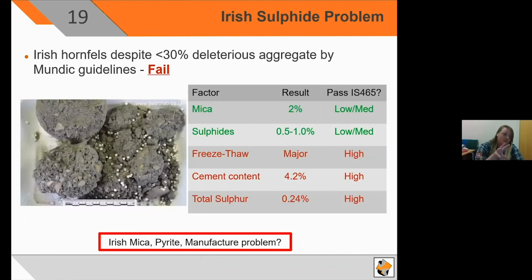So here's some figures from this particular type, which we did as a research and development task. Mica, 2%. That would theoretically be a low medium classification, if not almost negligible. However, failed the freeze thaw, gave a high result. You wouldn't expect that. Sulfides, 0.5 to 1%. It's not as bad as some of the greater than 1% to 2% aggregates. So it would technically give a low medium.